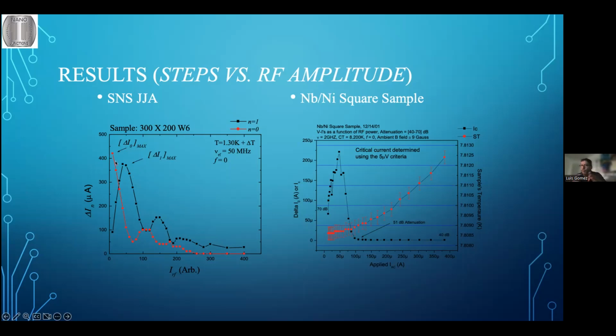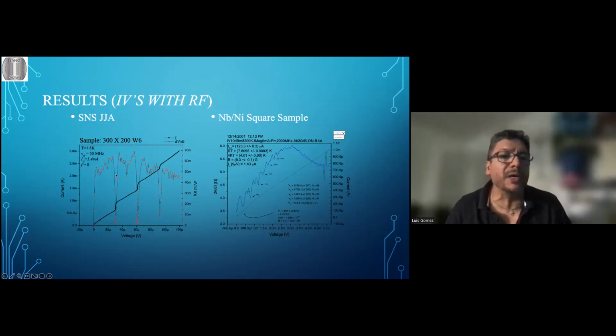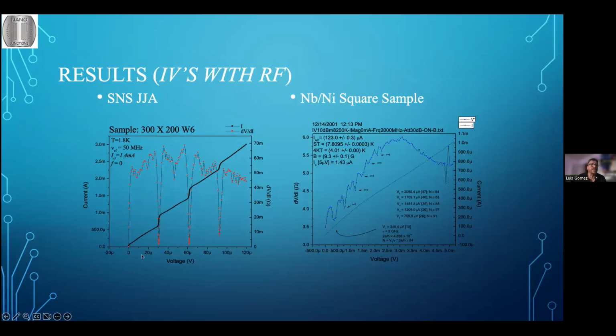And so I do many measurements similar to this one. The zero step will be the first one that occurs here. This is the first step, the second step, the third step, and so on. Then as I change the amplitude of the signal, in this case 1.4 milliamps, and I can change that to any value by changing this amplitude, the height would change, so it will be bigger or smaller, and then I plot that on this graph.